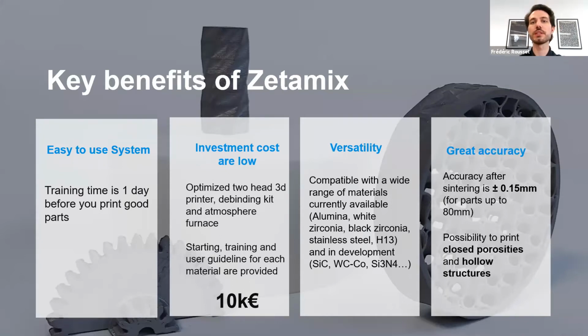A lot of people can think that FDM isn't quite accurate, but it is very good depending on the part that you need. Of course, it is not comparable to SLA in terms of accuracy, but you can go to 0.15 millimeters for parts up to 80 millimeters. So this is a very good accuracy for the process. And of course, the benefit of 3D printing is that you can print closed porosities or hollow structures that are quite difficult or even impossible to do with traditional processes.